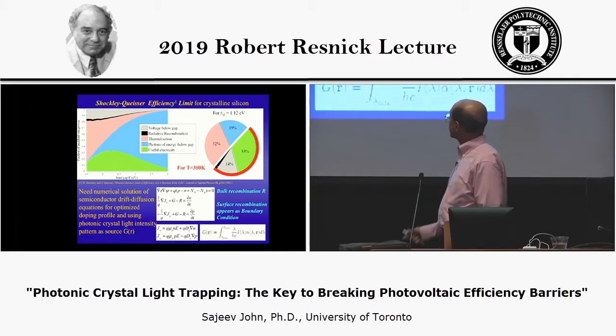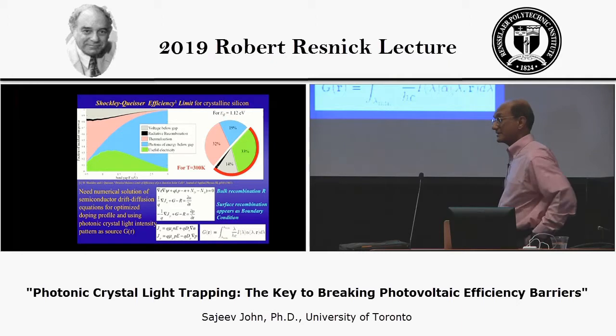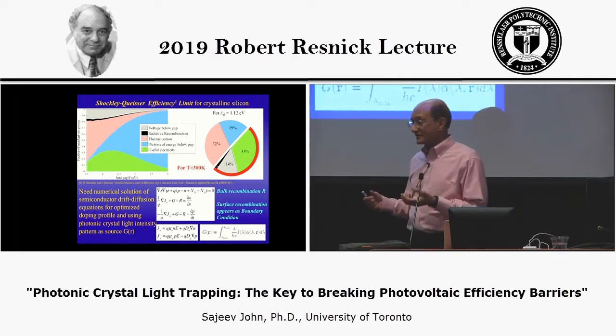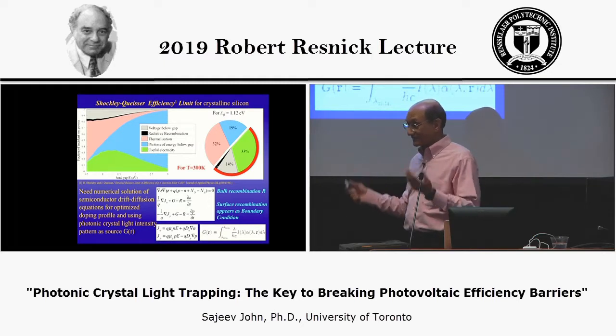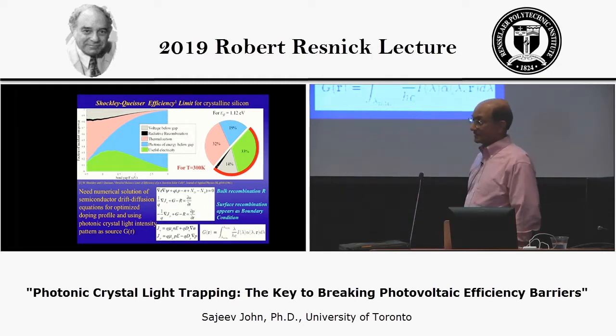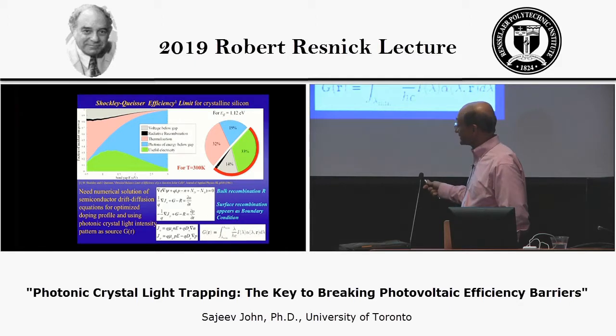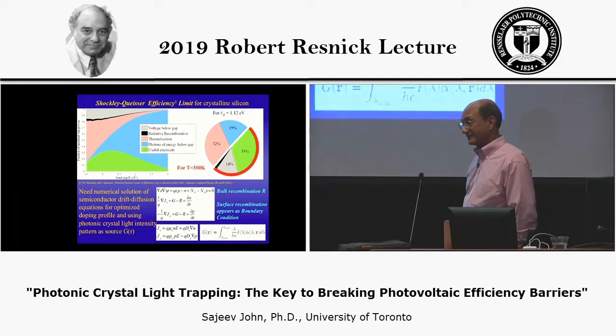For the surface, as I mentioned, it is treated as a boundary condition. It's referred to as a surface recombination velocity. If that velocity is very high, that means there are a lot of defects. Yeah. But we'll try to make some contact with actual experimental studies of the surfaces and the ways in which those have been passivated to put in the right numbers into these boundary conditions as well as the bulk recombination. Maybe we can pursue this more in the question session. Sure.